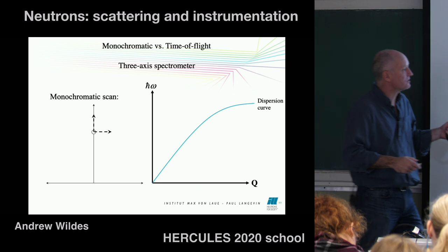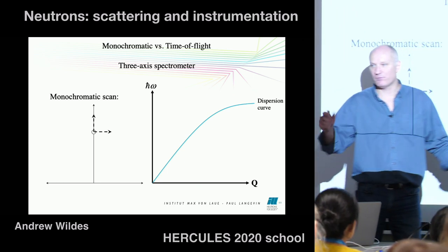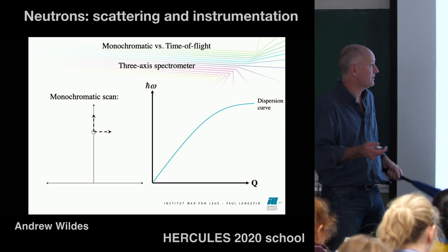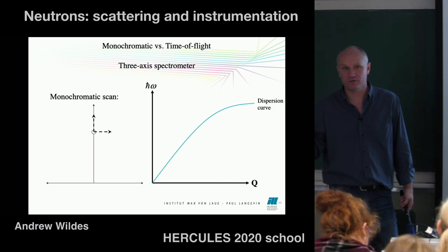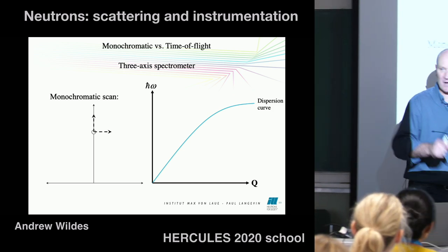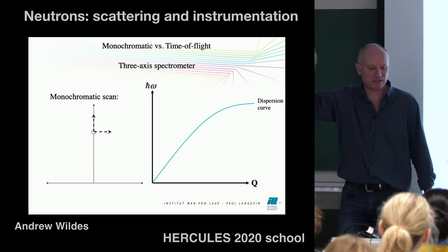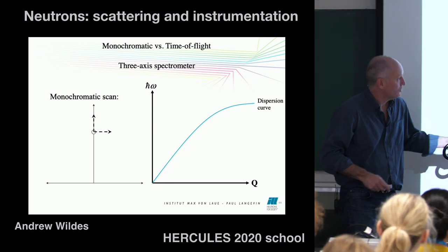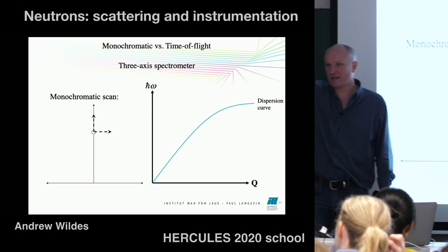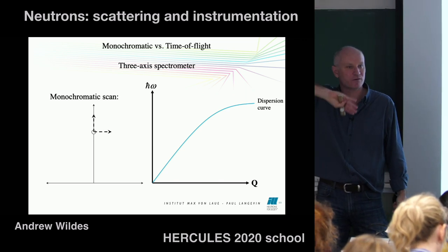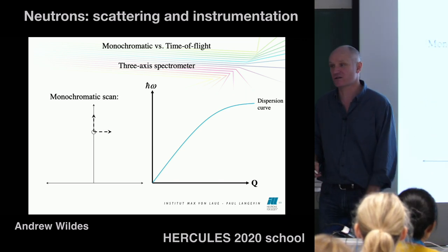Now, I showed you yesterday a dispersion curve, for example, from a phonon. If you wanted to measure this, particularly if it's from a single crystal, then you need to worry about the direction that the phonon is going in reciprocal space. You'll get some sort of energy transfer. You've got some energy associated with the phonon. You've got some momentum here associated with the phonon.